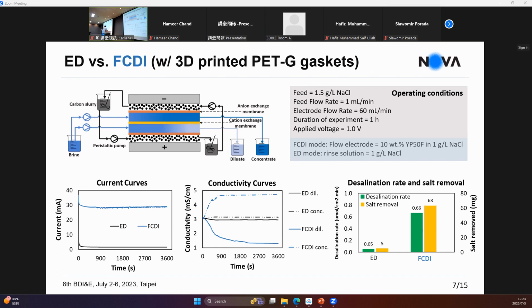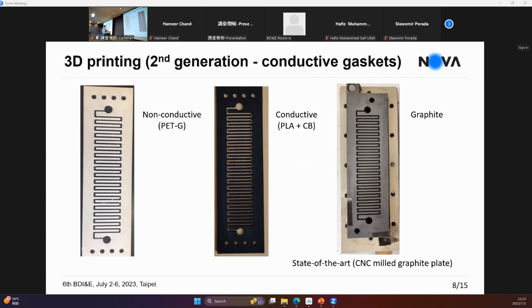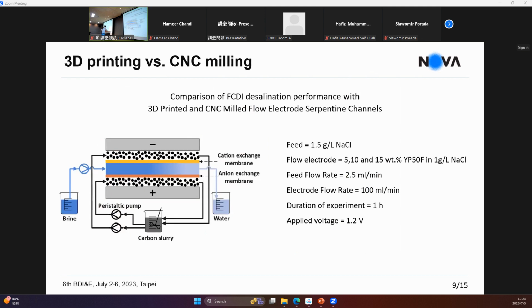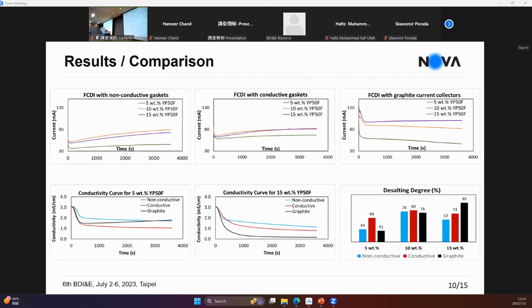But obviously, the correct benchmarking would always be to compare with graphite current collectors. So finally, we managed to produce our graphite current collectors. But meanwhile, we also 3D printed a conductive gasket made of PLA, polylactic acid, and carbon black. So the filament which we used for 3D printing was a mixture of these two things, and the carbon black basically adds conductivity to our material. And we did a comparison now only in FCDI mode. We performed a new desalination experiment with 3 stacks, with non-conductive space gasket, with conductive gasket, and with graphite current collector. And these are the results.